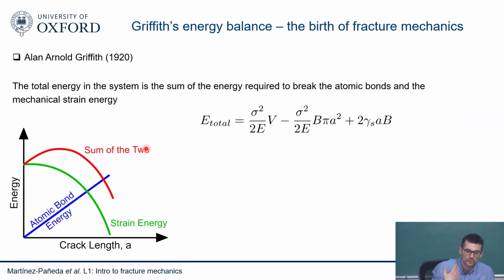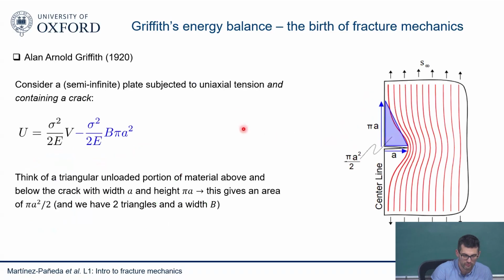Because the total energy in the system is going to be the sum of the energy required to break the atomic bonds and the mechanical strain energy. So this is the whole thing. Remember, this is the energy required to break the atomic bonds. For a crack to grow, I need enough energy to separate those atoms apart. This is what we discussed before: 2 times the surface energy times the length of the crack by b. And this is what we just derived before, right?